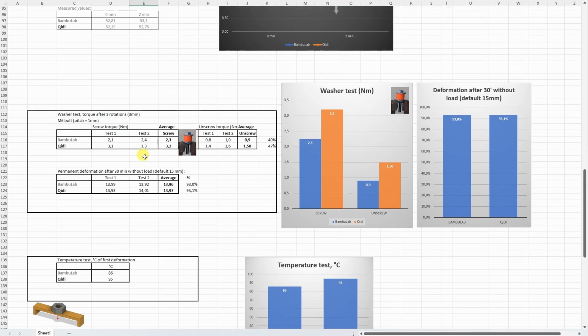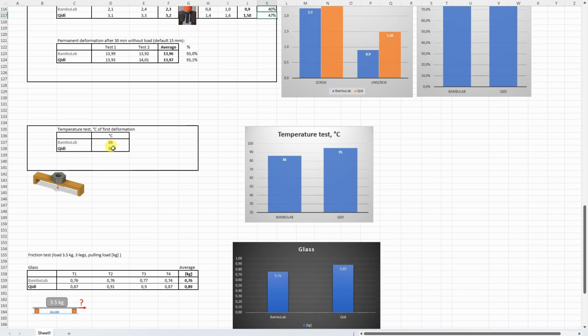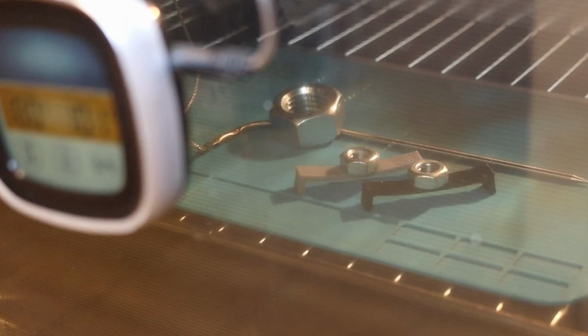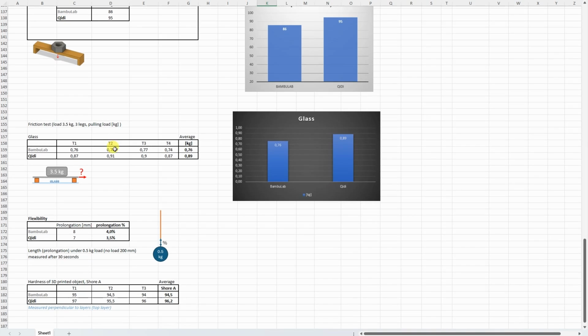And then that washer test, here again we can see some bigger differences, so I needed more torque to compress this washer 3 mm, but also the untightening torque was bigger too. But for me it is very important the ratio of these two numbers, and in this case it was better with the Qidi filament. On the temperature test, well, it was really hard to see when it starts deforming, but here you can see a screenshot, so definitely the Qidi filament was slightly better in this test. On the friction test, these are really surprising results. I'm not sure why, but actually the bigger friction I got with the harder material, with the Qidi.